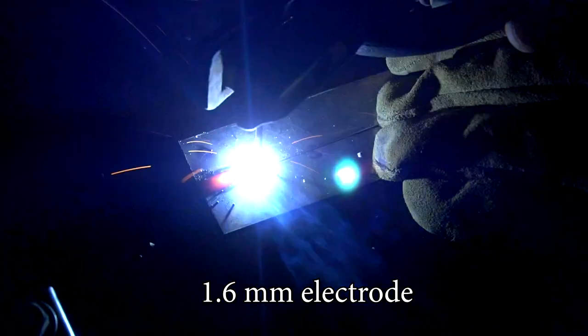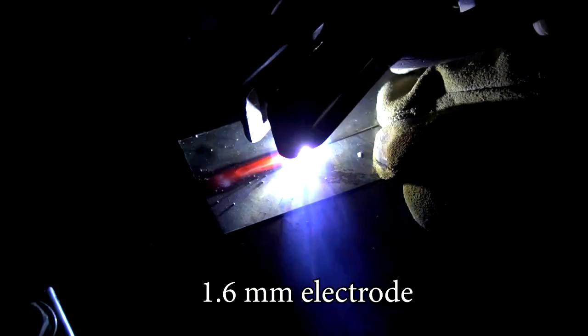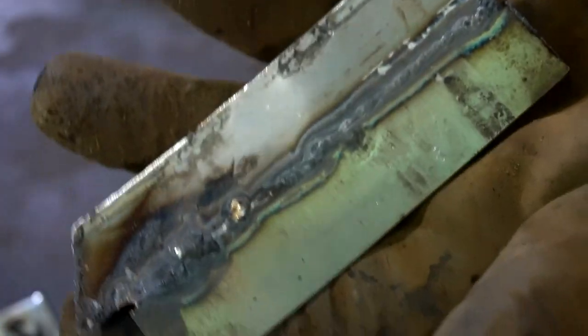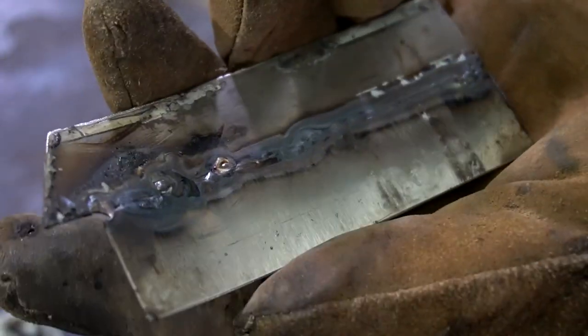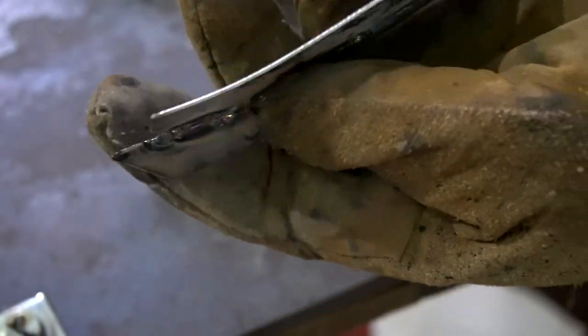I also found that the blowholes are pretty easy to fix with a 1.6 millimeter electrode as compared to 2.4. It is also easy for 2 millimeter, but you have to be very careful not to spend too much time over a certain area, because that will eventually increase the size of that hole. I surely don't use the fast drag method a lot, but I would say that with a couple of practice you will definitely be able to run a straight bead.